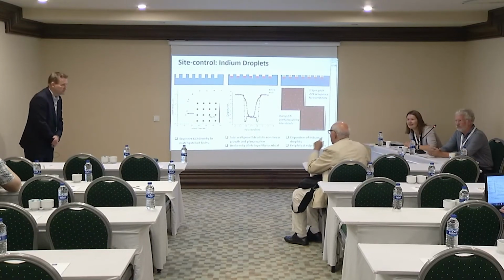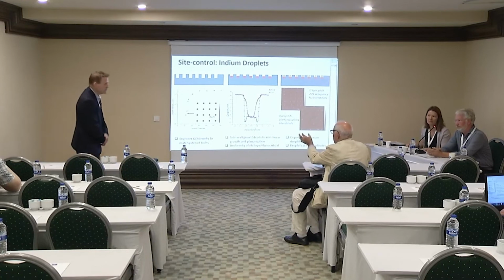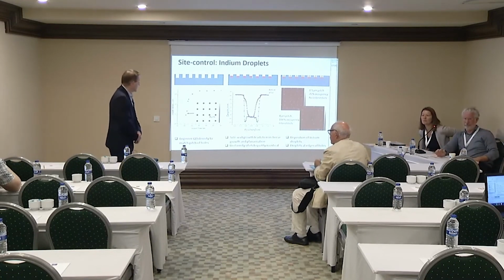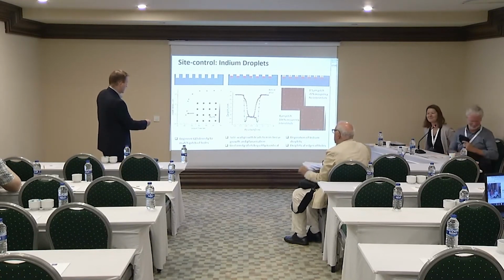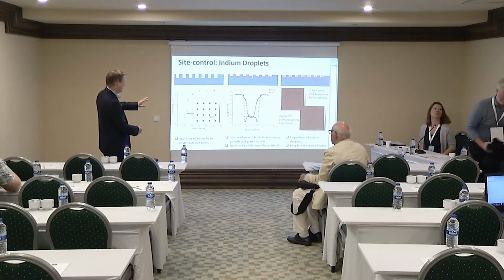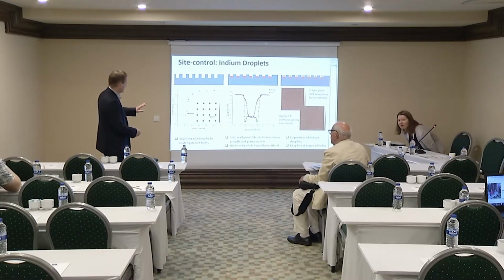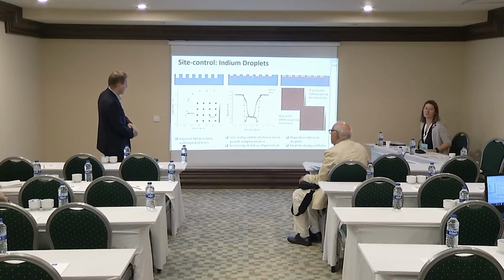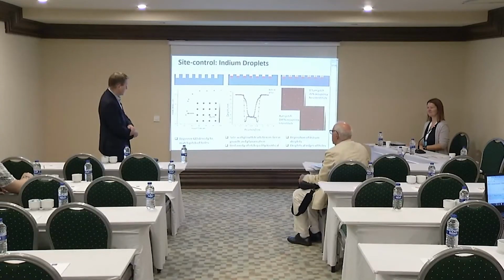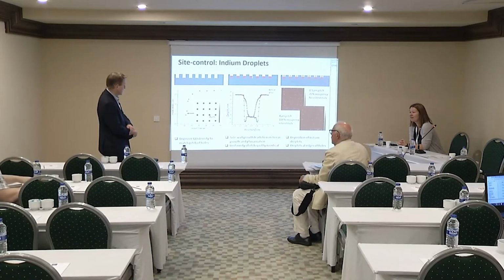Are there perspectives to increase the separation to a few microns? Yes. This is just summarising a lot of work that we've done. I mentioned earlier that we use 4 microns here because we want to optically address individual dots. Our excitation spot is about 2 to 3 microns or so, so we want these separated by quite a lot so we can look at individual dots.